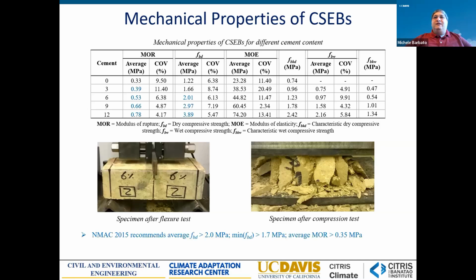What we found is that most of our composition had a sufficient modulus of rupture, the one that is obtained from the flexure test that is really measuring the behavior in tension and the brittleness. Then with at least 6% cement, we had a sufficient compressive strength. And then in order to achieve a compressive strength under wet condition as that is suggested in the literature, we actually had to use a relatively large amount of cement that are 9 and 12%. And again, this is mainly due to the fact that the soil was not the best soil to start with.